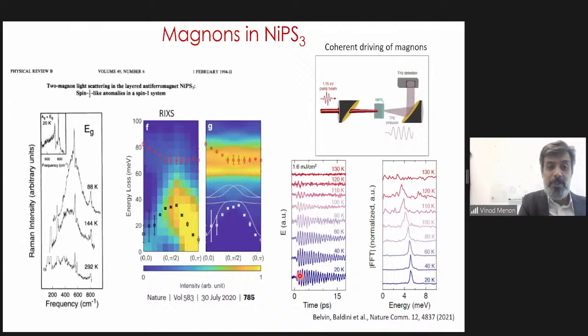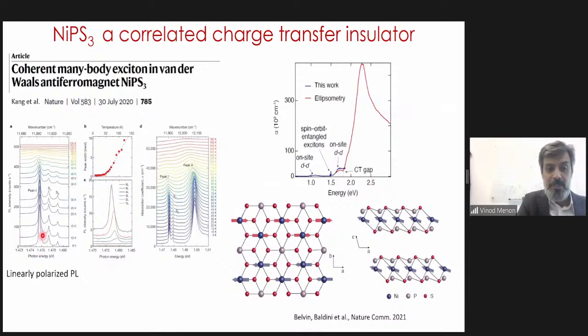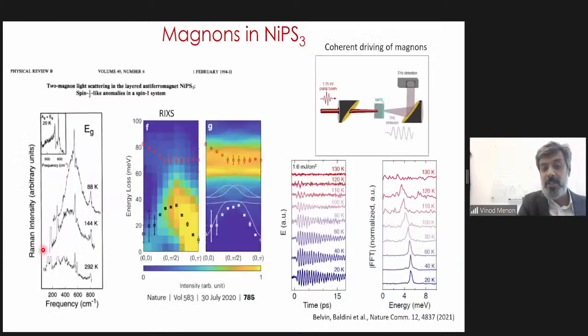And the intriguing thing about this material is that, because they have these spin chains, they host magnons or spin waves, and the spin waves have been studied in the past. You can see them with Raman experiments. You can see them with far infrared measurements or RIXS type measurements, where they see these magnon bands. And there have been some experiments where they've shown that you can drive these excitons, and you can watch these magnons oscillate in the terahertz. So that's also very intriguing, that you can actually drive the magnons by driving the excitons themselves.